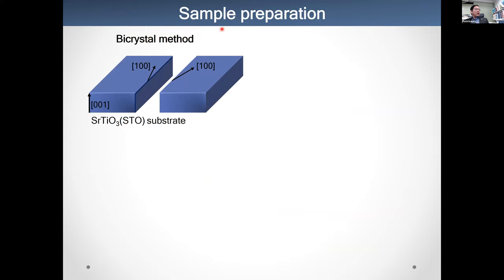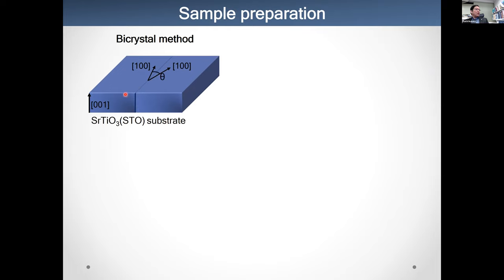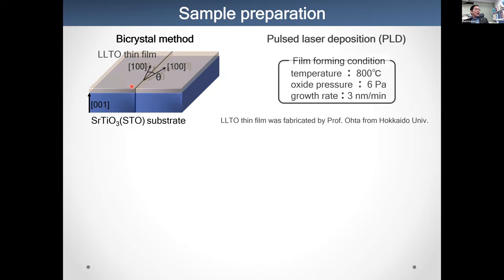Okay, let me introduce the sample preparation. For LLTO, we can't obtain a single crystal. This is very difficult. So we first use a strontium titanate bicrystal made by hot pressing. This is easy to make. We use this as a substrate for LLTO growth. We deposit the LLTO thin film by pulsed laser deposition, and the film growth condition